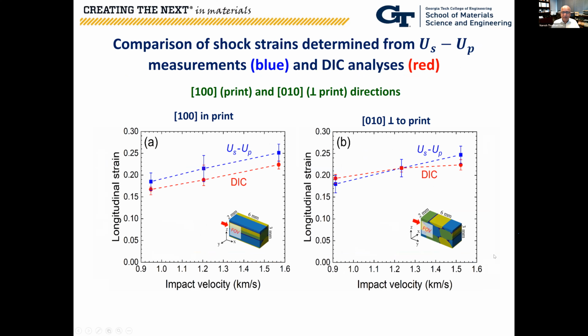Another measure of the success of the correlations: here I'm plotting the longitudinal strain as a function of impact velocity, the DIC measurements, and then you can also use the USUP data that we generated. You can use the constitutive equations and convert those to strains from that USUP data. And you see for the 1-0-0 print condition, the two show some difference, but not much in terms of the peak strain they are monitoring.